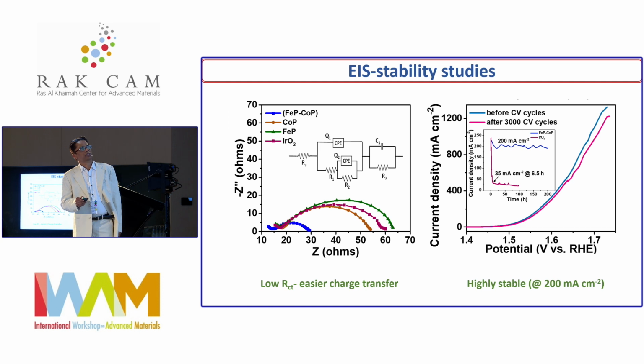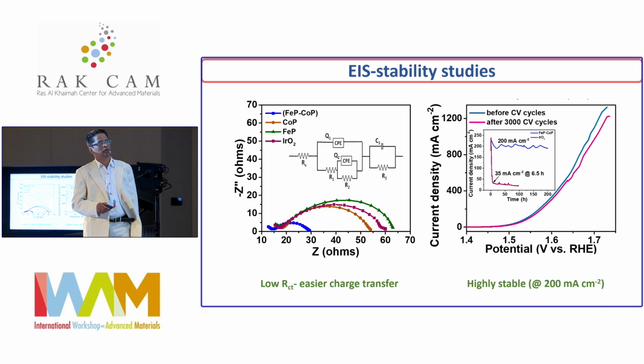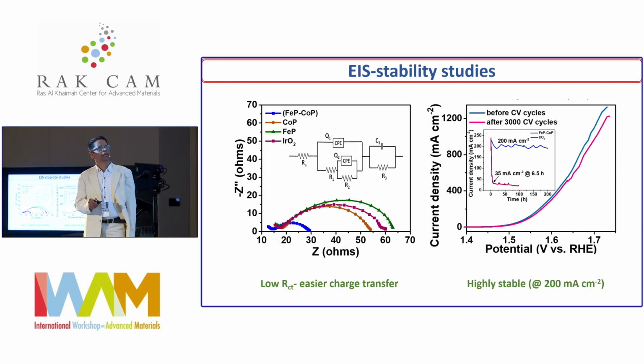You can also see very high stability. At almost 200 milliampere per centimeter square, you can keep this stable for 200 hours, whereas iridium oxide is not stable even for 50 hours at this current density, at a constant potential. It's also almost stable for 3000 CV cycles, indicating the robust activity of this mixture.